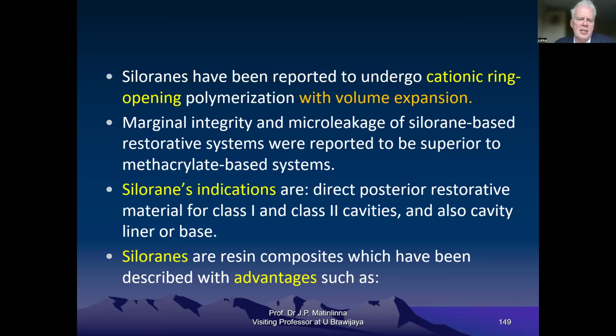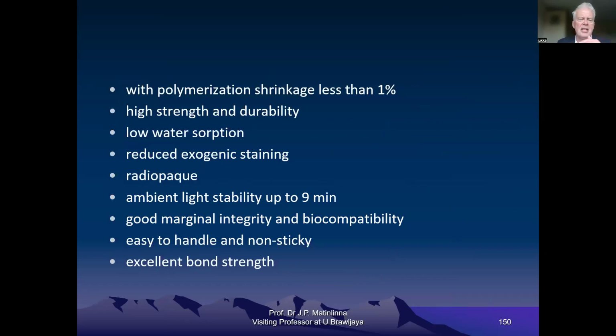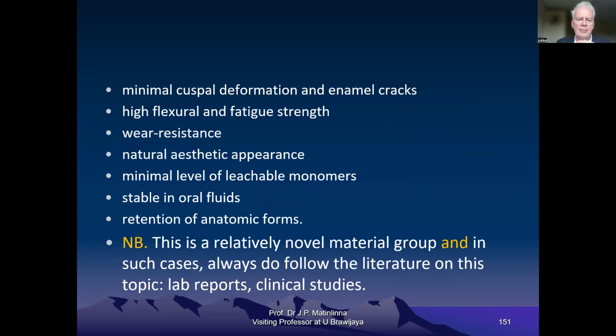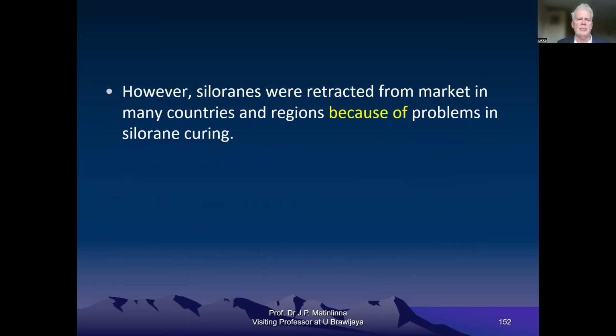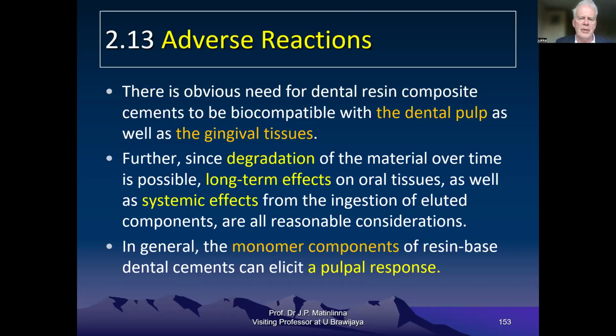Silorane resin composites have been described with several advantages. We can see here low water absorption, reduced extrinsic staining, radio-opaque, ambient light stability, easy to handle and non-sticky, excellent bond strength. It's a very long list. Wear resistance is also mentioned. However, this is still a relatively novel material group and we had better follow the literature. However, they were retracted from the market in many countries and regions because there were problems in the silorane curing, as attractive as it appeared to be.